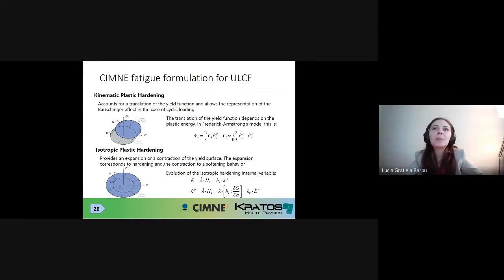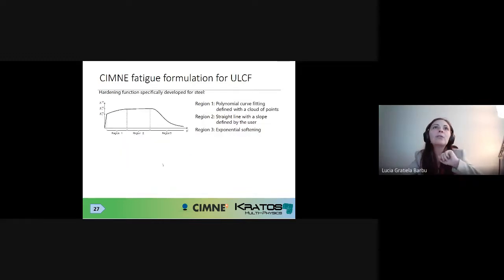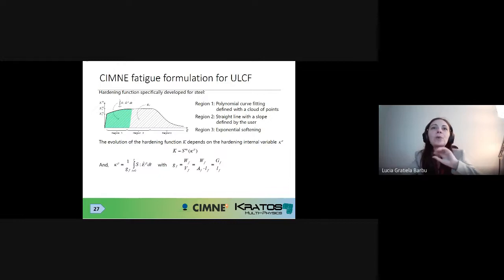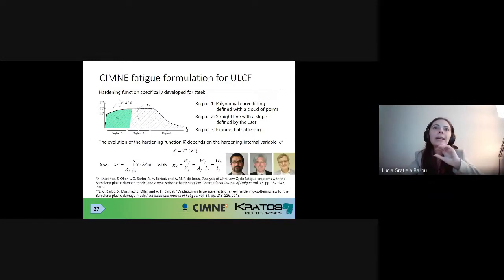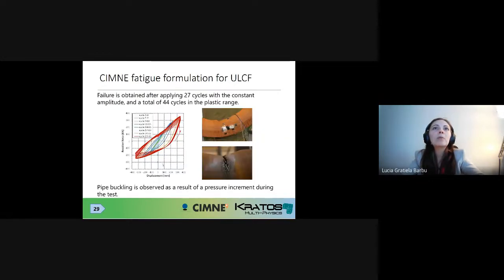This is a model which was proposed in 2015, and I don't want to get into details because we formulated it then and we haven't used it for the past years because we didn't have research projects specifically focused on this. Just take into account that it uses kinematic plastic hardening coupled with isotropic plastic hardening. We have a specific constitutive law developed for that, and you can find the expressions, which are based on the fracture energy, inside these papers that I will put here. This work was developed during my PhD with the supervision of Professor Xavier Martinez, Sergio Oller, and Alex Barbu.